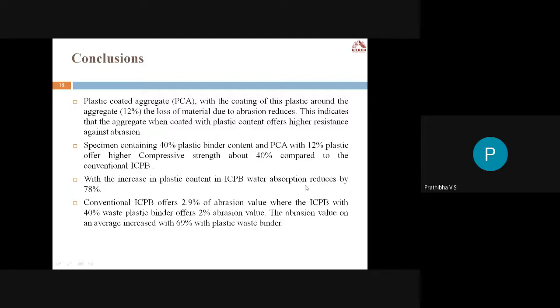Coming to the water absorption, it is reduced by 78%, and also the abrasion value of the ICBP block. For the conventional ICBP block, the average abrasion of both tests, Los Angeles and surface abrasion, is around 2.9%, whereas the ICBP with PCA and plastic binder of 40% offers 2%. So there is a reduction of 69% with the plastic binder. So it is even economical, and we can see the strength parameters and also the abrasion resistance. It is more helpful to use plastic waste in interlocking paving blocks.